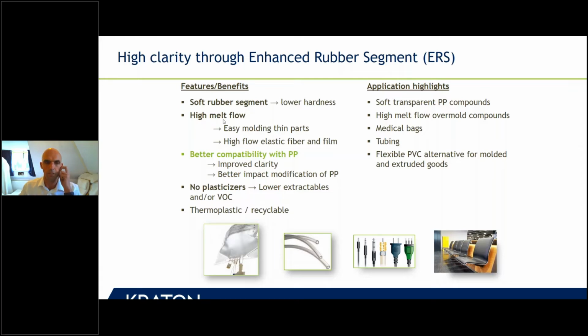And we made one, and we did it actually through an enhanced rubber segment. So we redesigned the rubber segment of our styrenic block copolymers to meet better the requirements for transparent, flexible compounds. So the enhanced rubber segment, the key thing there is that we increase the amount of vinyl. So if it's a butadiene-based rubber polymer, as you probably know, you can polymerize that in a 1,4 way or in a 1,2 way. And in the latter case, you get more vinyls. And then, of course, you hydrogenate them in this case, but within the company, we call it high vinyl.